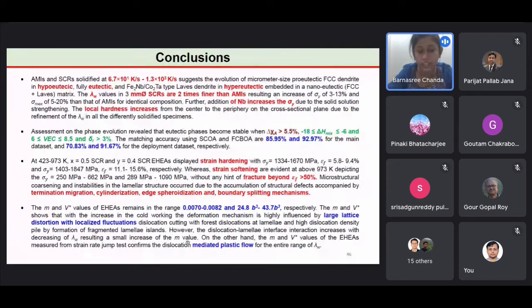The strain rate sensitivity and activation volume remain in the range of 0.0070 to 0.0082 and 24.8 b³ to 43.7 b³, which suggests that the deformation is dislocation mediated. The TEM image shows a large lattice distortion with localized fluctuation. Also, the strain rate sensitivity and activation volume values for the eutectic high-entropy alloys were measured. So the strain rate jump test confirms the dislocation mediated plastic flow for the entire range of average eutectic lamellae thickness.